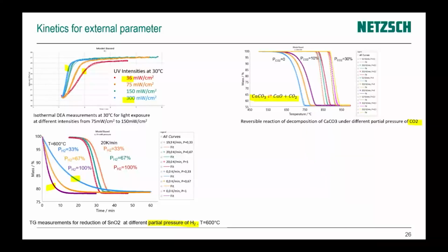high partial pressure of CO2, then decomposition is suppressed and decomposition happens at high temperature. Without CO2, without carbon dioxide, decomposition happens at early temperature.